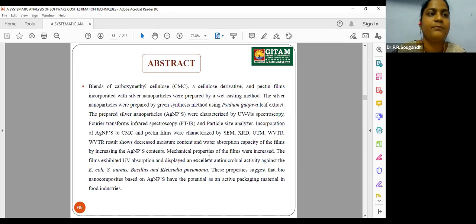Later, the prepared silver nanoparticles were characterized using UV visible spectroscopy, FTIR, and particle size analyzer. After that, the incorporation of silver nanoparticles into the biopolymers was characterized by SEM, XRD, UTM, WVTR, and antimicrobial studies have also been done. With these studies, we can see that there is an increase in the mechanical properties, barrier properties, and all the characteristics by the incorporation of silver nanoparticles into the biopolymers.